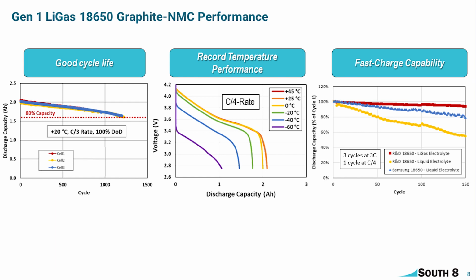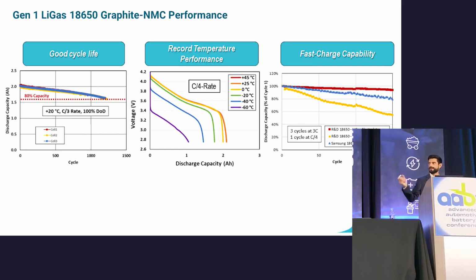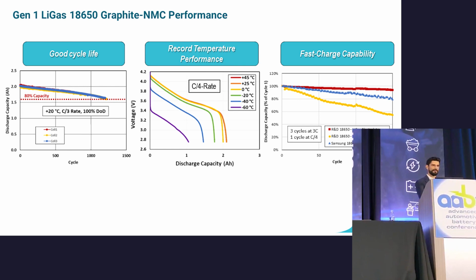We thought that was a really big gap, so we just went online, bought a regular old 18650 Samsung cell and ran that one with the same fast charge protocol, and we're still outlasting that Samsung cell. We had a good talk earlier from Frederick, thank you, discussing the lithium plating on the graphite under some of these protocols. So we know our LiGas electrolyte has a very highly conductive SEI layer, enabling fast migration of lithium through that SEI, so it prevents a lot of lithium plating under these fast charge protocols.